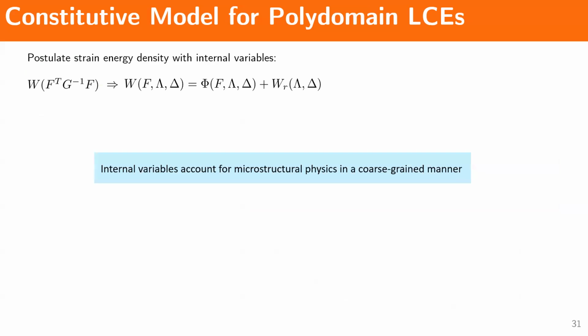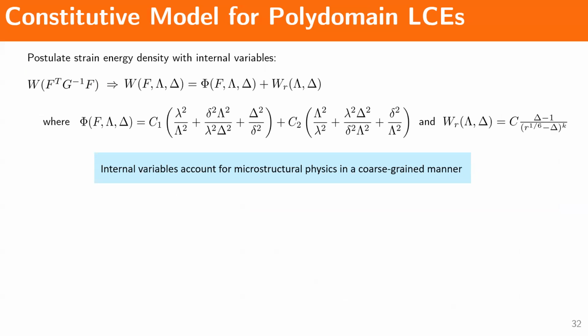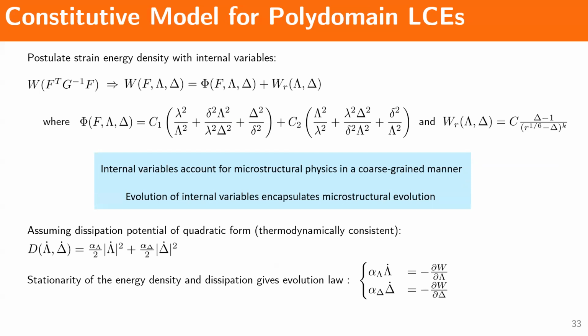And so now we can postulate the strain energy density for these materials. It will be some elastic energy with respect to the new ground state, which is the G tensor here, the spontaneous deformation state furnished by these two internal variables, lambda and delta. Here's our specific form, but the specific form of the energy doesn't really matter. We're just using the internal variables lambda and delta, the spontaneous deformation in the mesoscale, to account for these micromechanics in a coarse-grained manner to give us our macroscopic stress. The evolution of the internal variables encapsulates our microstructural evolution as well.